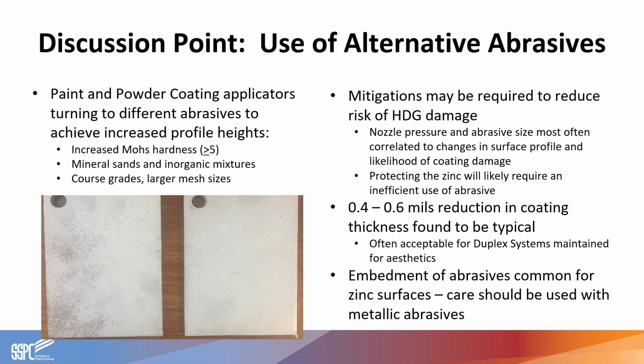The typical galvanized coating on structural steel is often in the neighborhood of 4 to 6 mils. So even considering a reduction, many times there is sufficient zinc that remains above the initial specification requirements after blasting. Another thing to consider with duplex systems is that many duplex coatings are going to be maintained for appearance. So again, this reduction in coating thickness, you need to determine if that's acceptable for the project. If there is the potential for low coating thickness, you can address that in the project standard, whether that needs to be repaired or just addressed in some way.